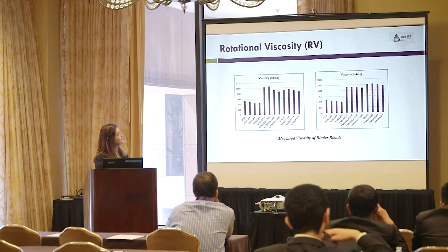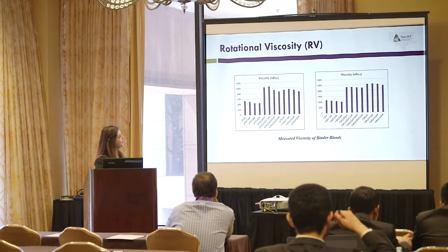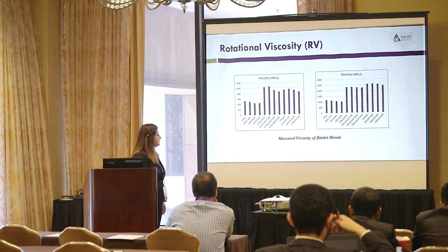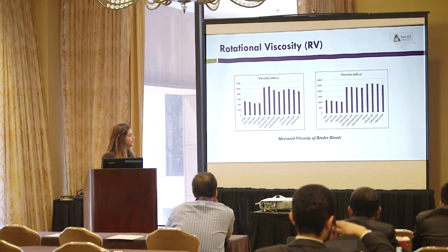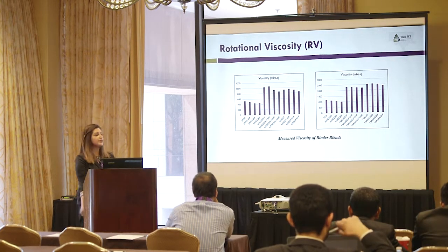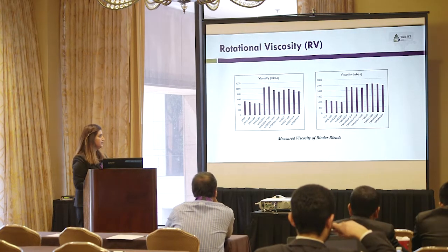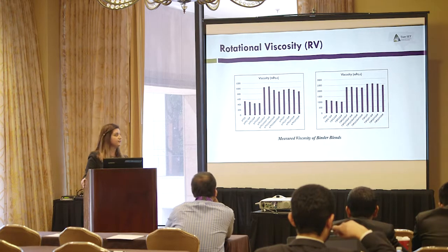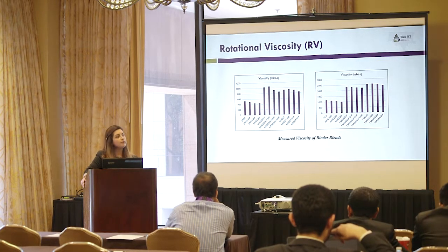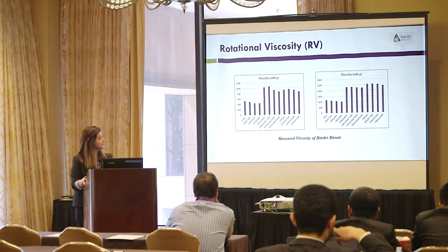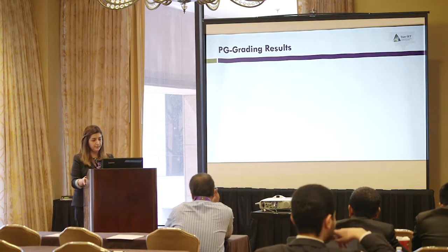This slide presents the viscosity of different binder blends we prepared. We have the result for unmodified binder and the modified binder. Addition of the recycled asphalt material caused an increase in the viscosity of the binder blends, and when we added 1% of self-healing polymer, we weren't able to see a significant change, but by increasing the amount of self-healing polymer in binder blends, we were able to see a decrease in viscosity, which shows an improvement in workability of the binder blends that have recycled asphalt material.